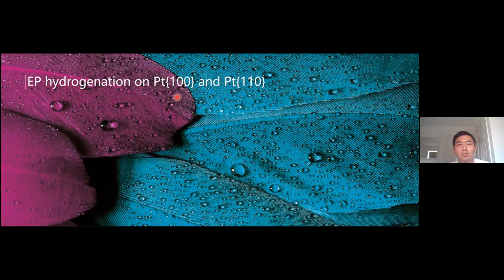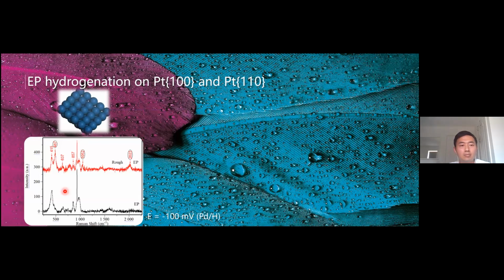So how about platinum 100? Similar results from platinum 110, because it's a very close compact ordered surface. We didn't see the half hydrogenated state - instead we saw the precursor. Then when it's roughened, we saw both states appeared on the surface.